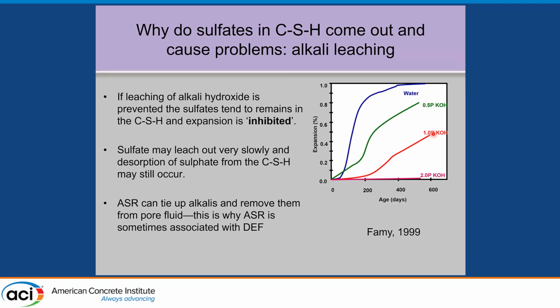But when you reduce the high hydroxyl ion concentration in the pore solution, the expansion started to climb, and in pure water got the most expansion because it's leaching out the sulfate from the CSH, and it's reacting to form this delayed ettringite. This somewhat ties up to ASR because often DEF was associated with ASR damage because ASR also binds up alkalis and takes it out of the pore solution, reduce the pH somewhat, such that you might get expansion.